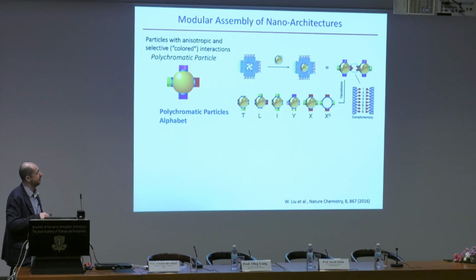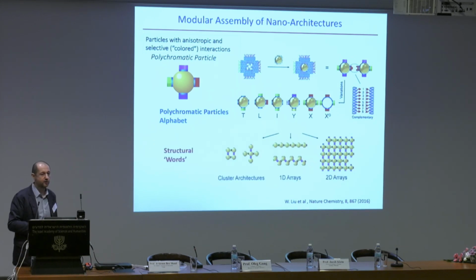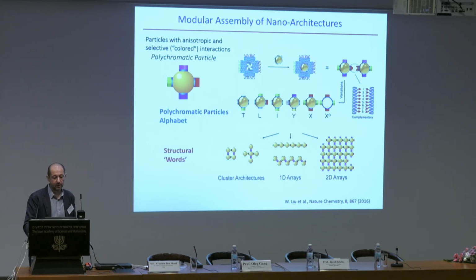We have a DNA origami where the particle sits inside, and there are a number of DNA strands. It's not one, it's 8 of them, which are different, that allow us to encode this color. So the color is not provided again by one DNA, but rather by 8. Now when you build different types of structures, essentially you're mixing different types of these letters, and you create different types of words. You can get both periodic and non-periodic structures, clusters, 2-dimensional and 1-dimensional arrays, because everything done here is planar.